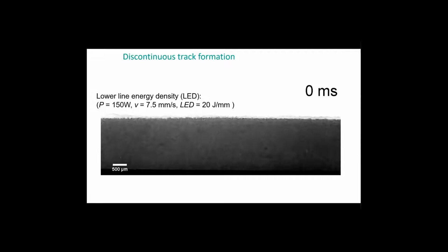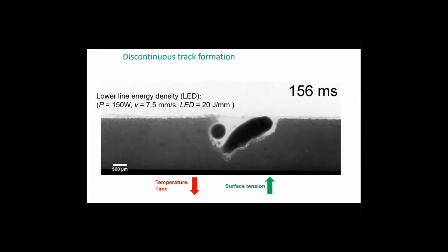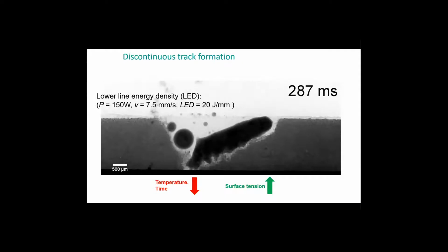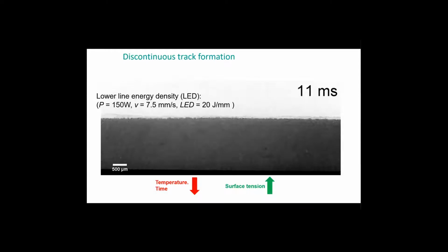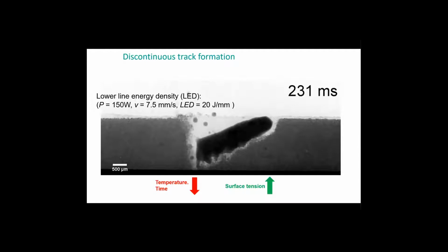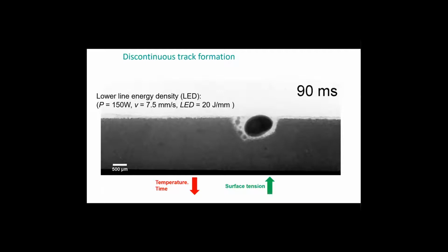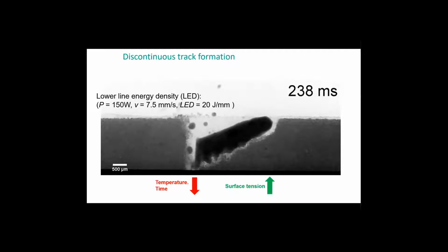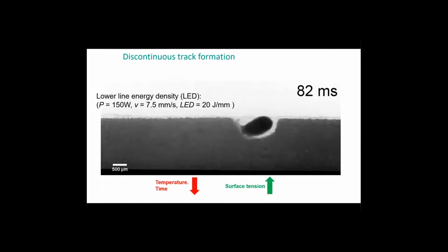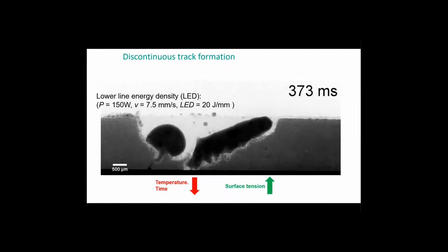Similarly, you can see when you travel too fast or the energy is too low, then you will end up with a discontinuous track formation. And there are plenty of other defects that you can study using X-ray radiography. You can see here that these are images taken over fractions of a second, and you can see, for example, the loss of powder, and you can track those in real time. So there's much to be gained by imaging in real time in radiography, but there's also a lot of value from